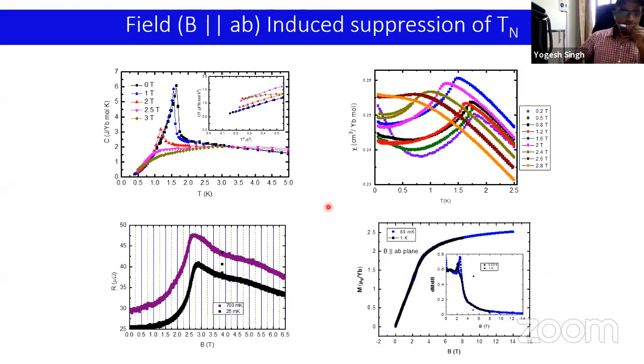Now I show you that a magnetic field can be applied to tune the TN continuously to 0. So this is the specific heat versus temperature at various fields. The field is applied perpendicular to the c-axis, so in the ab plane. And you see that the ordering which is seen at 0 field is suppressed continuously to low temperatures. Additionally, the susceptibility versus temperature at various fields was also measured. And this also shows that the ordering temperature is suppressed continuously to 0 temperature. And we can do various other measurements which confirm this. I would like to point out here that the resistivity versus field as well as M versus field, when you take the derivative, they also show another anomaly, a weak anomaly here, which moves up with temperature.